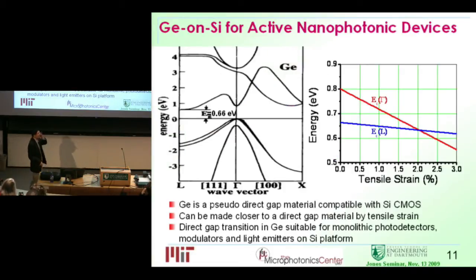So how about active devices? Active devices in photonics usually refer to lasers, modulators, and photodetectors. We're actually using a material that's already being used in silicon microelectronics, which is germanium. Germanium is doped into silicon to create strain in the silicon layer to enhance the mobility of carriers so that it can run faster.